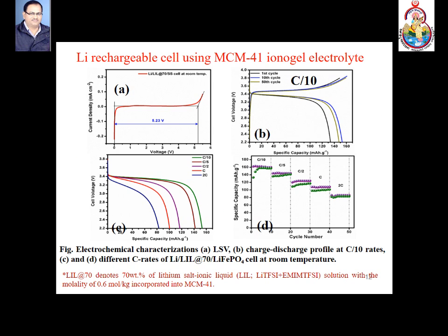One of the important properties of such ionogel electrolytes is that they do not suffer from the effect of dendrite formation or dendrite growth when lithium is used as anode material. Further, for such ionogel electrolytes, the discharge capacity is very high, and therefore these, besides suppressing the dendrite growth, have very high discharge capacity.